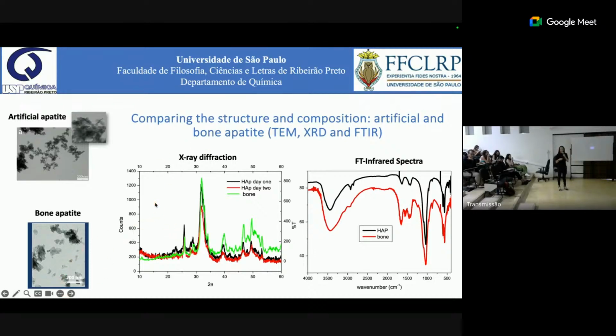Controlling the precipitation of apatite on the bench, in the laboratory, we are able, even in the absence of the confined medium, to get the formation of this artificial apatite with a structure very similar to bone apatite, and not only in the morphology, but also in the structure, as we can see here by comparing the X-ray diffraction of the bones and the apatite that we precipitated. We see that all the peaks are very similar and match the peaks of the X-ray diffraction of the bone. And also the infrared spectrum of the particles is very similar to the infrared spectra we found for the bones.